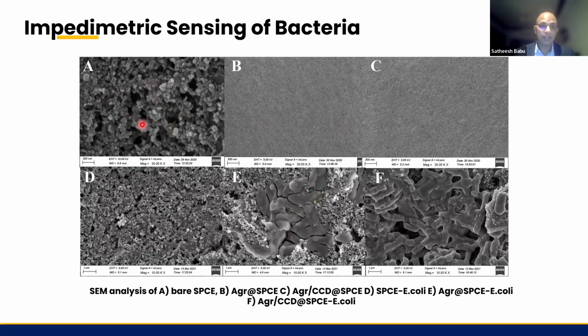So for example, this is the bare electrode where no modification was done. And when that is introduced into the solution which contains bacteria, we find that there are no bacterial cells on the electrode surface. And this is the electrode with only agarose, no carbon dots and no antibiotic. And there are a few cells on the electrode surface.